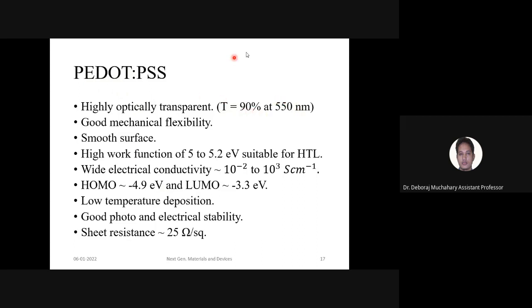And in our solar spectrum, if you see, the highest peak, the peak of energy of the AM 1.5 solar spectrum, is around between 500 and 600 nanometer, there is a peak intensity, right? So at around the peak intensity of the solar spectrum, that is at around 550 nanometer wavelength, the transparency is around 90%. So it is a good transparent layer. If you use it on top of the silicon, then the light can easily pass through it and fall on the underlying silicon.